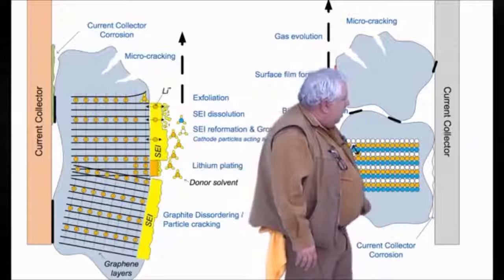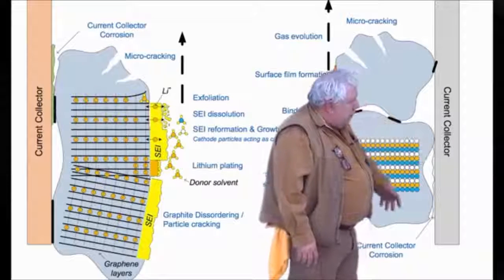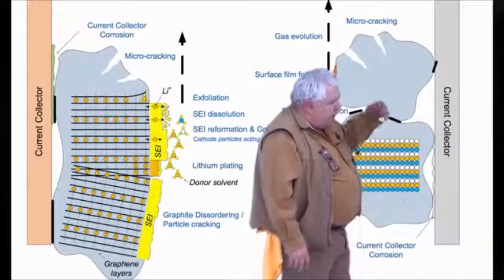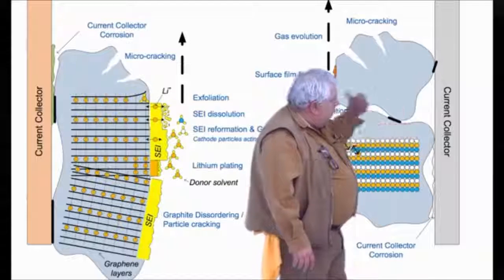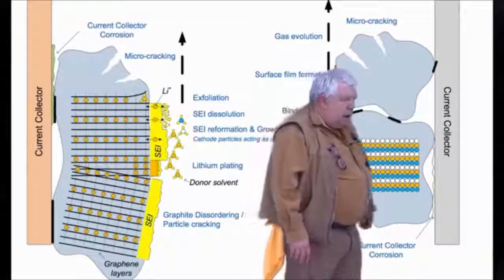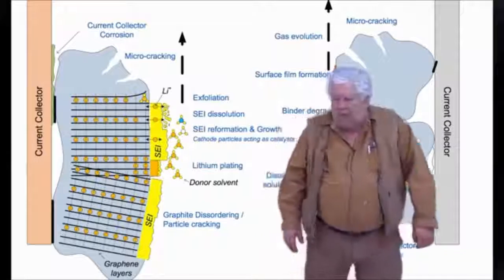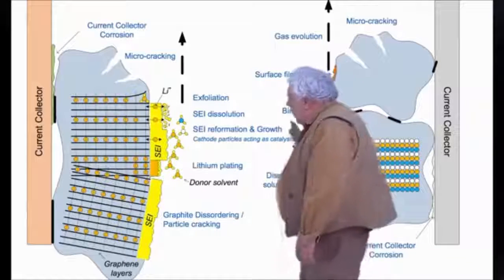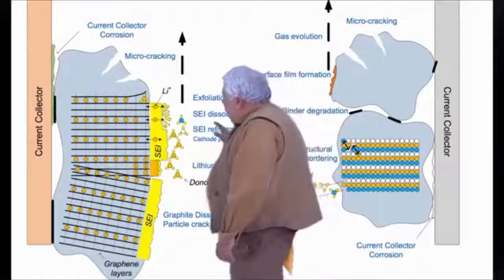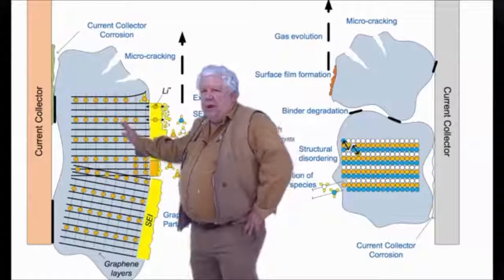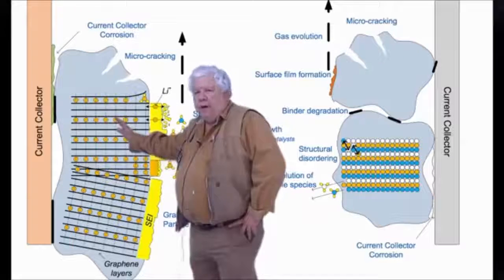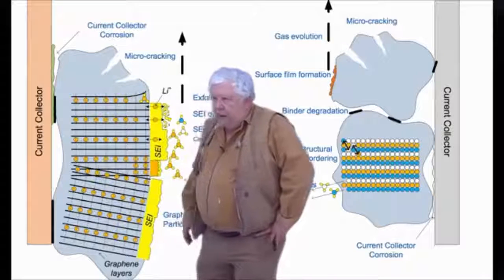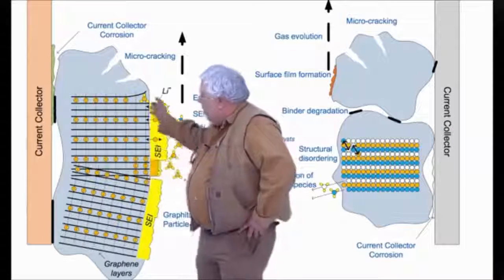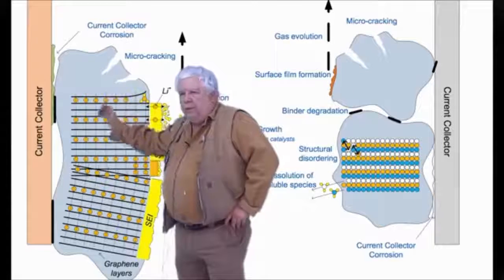Remember, the lithium ion just kind of tunneled in, but the iron was kind of bound to the phosphate. As we start to pull more negative charge off of this, making a more positive charge, the iron positive cation comes out. And it starts to migrate through the electrolyte. And it deposits on the SEI layer. And it will form dendrites. And it'll even form compounds with the lithium. And so now we have wounds and ulcers here.